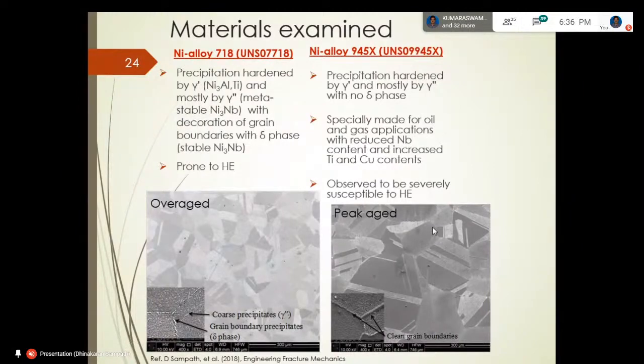And also there is another technique, thermal desorption method. In that case, first we need to charge the material with hydrogen and then heat it up to different temperature range until all hydrogen comes out of the material. So you will get to see the diffusivity as well as the binding energy and those kind of parameters. So you'll get the transport properties of the material.